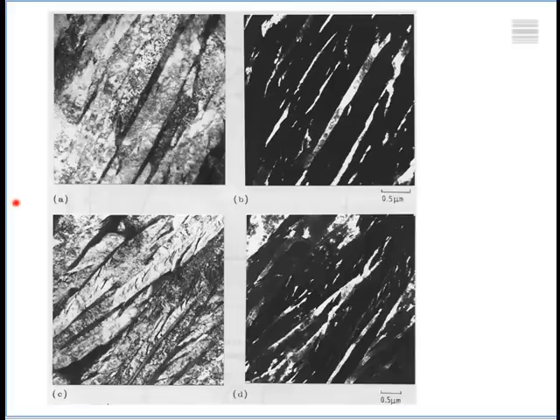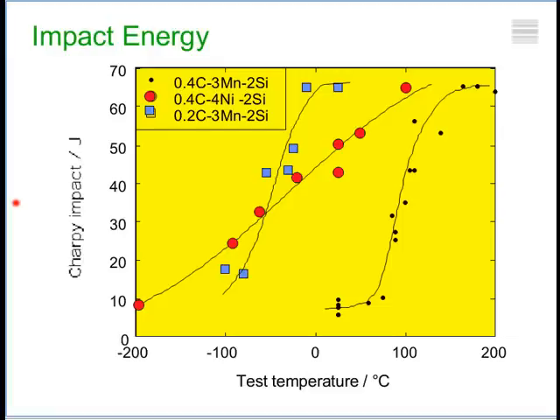And here we have shifted the T0 curve to a higher carbon concentration by removing the manganese and putting in the nickel. When you do that, so very, very simple theory to guide this principle, you get a shift in the impact transition temperature of almost 200 degrees centigrade. So we haven't done a very large number of empirical experiments, but we used the basic theory to get rid of the problem, and you can see large values of Charpy at very low temperatures.